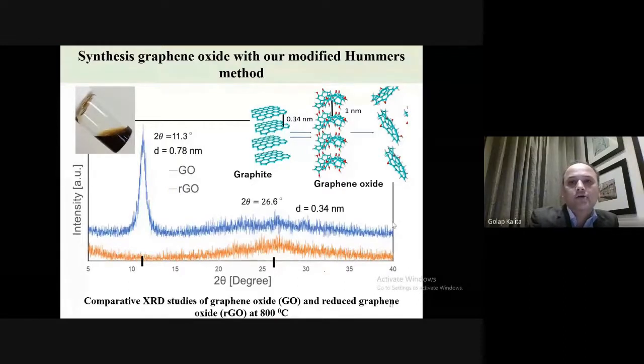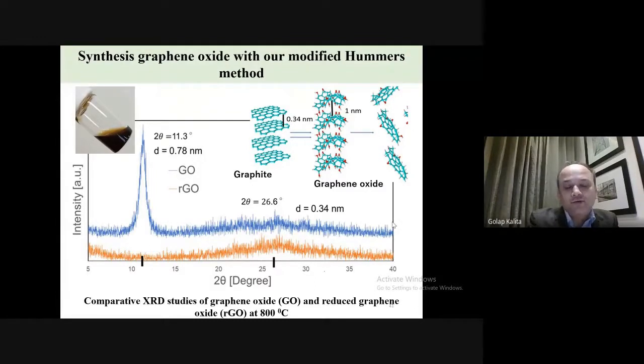by our modified methods, so we can produce it in very high quantity. We especially used some techniques in this synthesis, and this is a solution of graphene oxide. When you oxidize graphite, the layer distance between the graphene layers increases to around 1 nanometer in the oxide layers. When you measure the XRD, graphite has its XRD peak around 25 to 26 degrees 2 theta, but when you oxidize it, you get a strong peak around 10 to 11. So this corresponds to the graphene oxide.